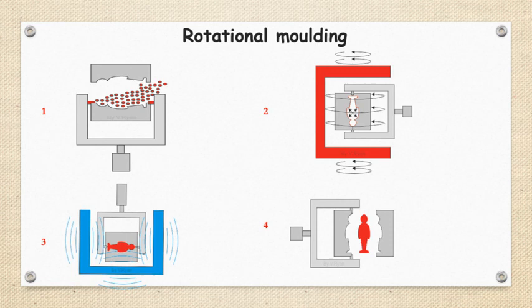It is closed and then transferred to the second stage where it is heated up to 300 degrees Celsius and rotated. That mold is rotated inside the heater with a moderate speed - not too high, not too low - at moderate speed. It is rotating in both directions: horizontal, vertical, in multiple directions you can rotate this mold.